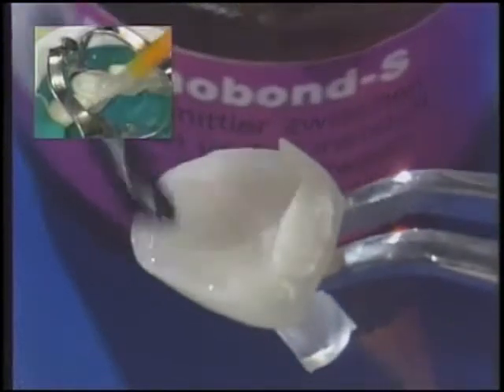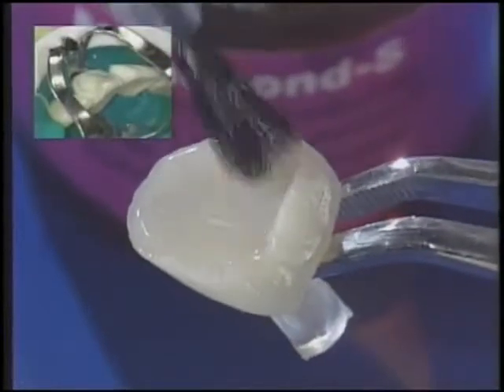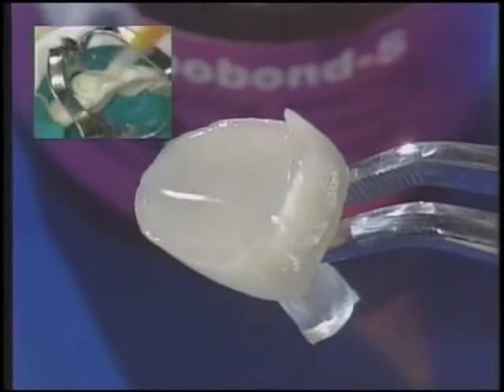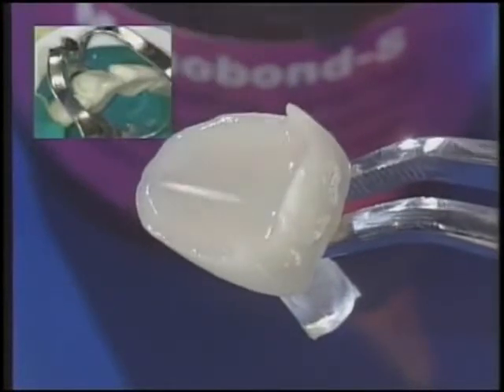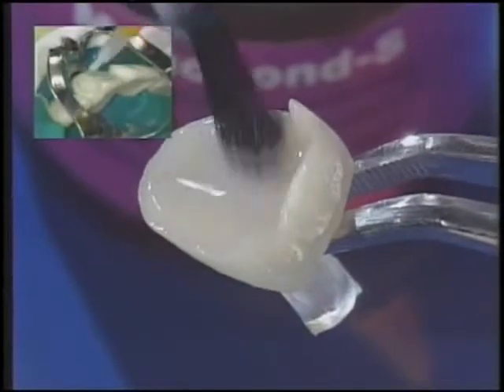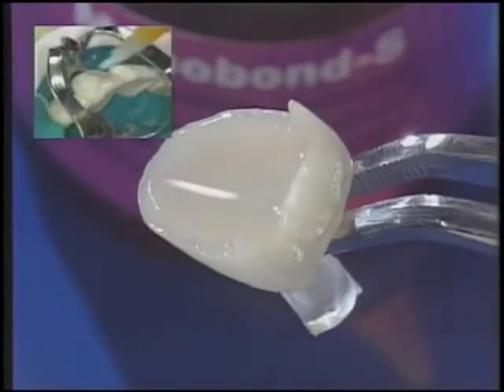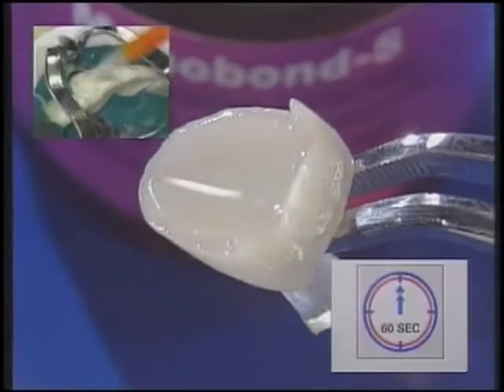Monobond S, a silane preparation, is applied to the ceramic for 60 seconds to achieve a bond between the inorganic ceramic and the organic resin. Syntac primer and adhesive help form a bond between the enamel, dentin, and composite. They prevent polymerization shrinkage of the luting composite.